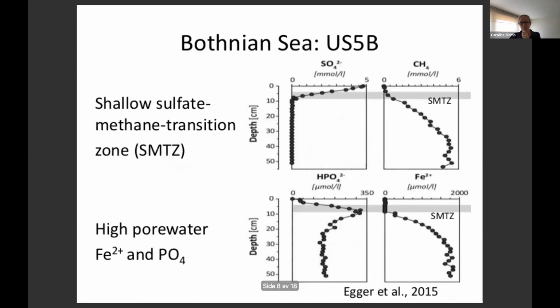Next slide, please. And what we see in these sediments is, at the top you see sulfate and methane, these react with each other. Below that, in a zone where there's no longer reduced sulfide, so no longer H2S, what we see there is extremely high iron. And I'm not sure you can all see it, but the concentrations there go up to almost 2 millimolar, which is really high. And we also see that phosphate concentrations directly drop off below that shaded area, below that sulfate-methane transition zone. And we've interpreted this as the zone that in this location, below the SMT, is where likely Vivianite is forming. So we thought this is a great place to assess if this is the case.